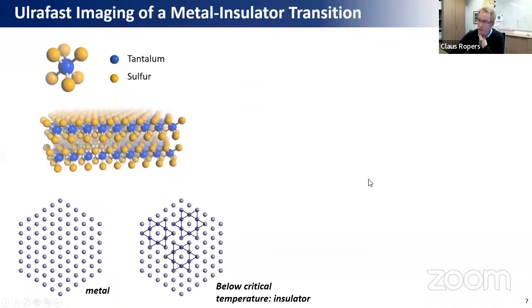Yes, so I should have included a slide. There's a lot of ultrafast angle resolved photoemission spectroscopy on this, which studies the size of the gap, the quenching of the gap. Here, our technique, in terms of the electron beam, is only sensitive to the lattice distortion, so to the crystalline structure. So it's very complementary to the ARPES work. In particular, in terms of scattering cross section, or structure factor, we are sensitive primarily to the tantalum atoms. So we're not very sensitive to the sulfur displacements. Mostly what we see is in-plane tantalum displacements.